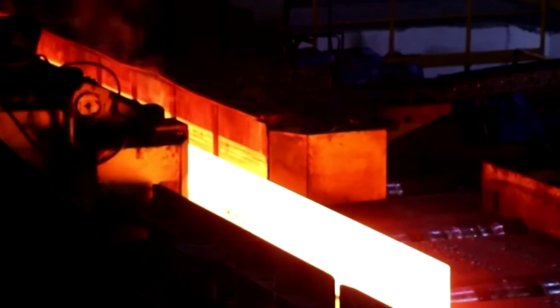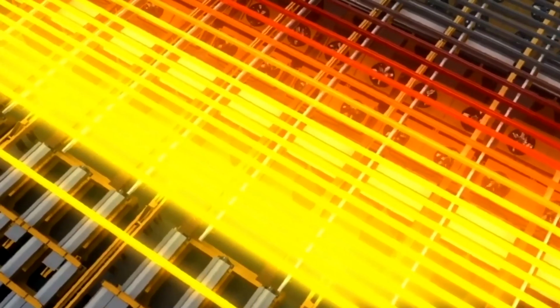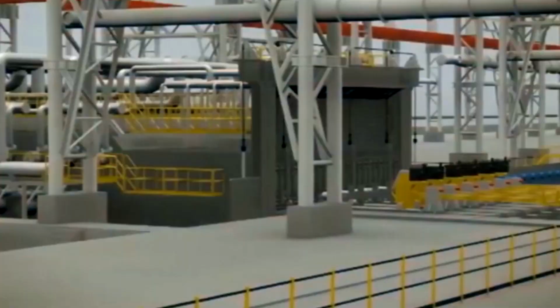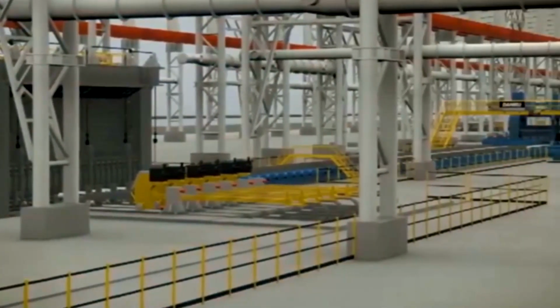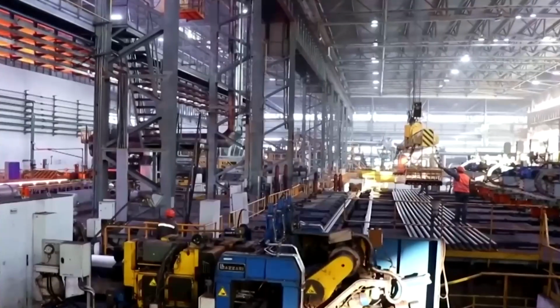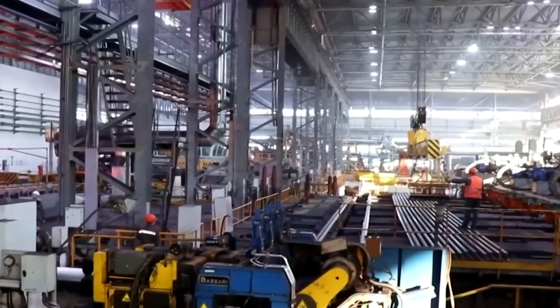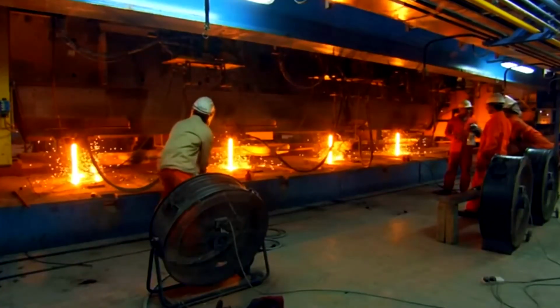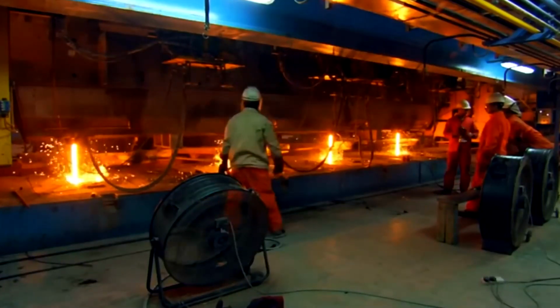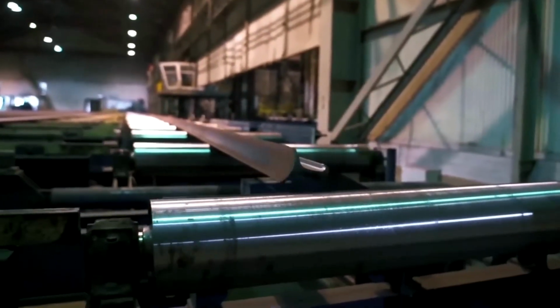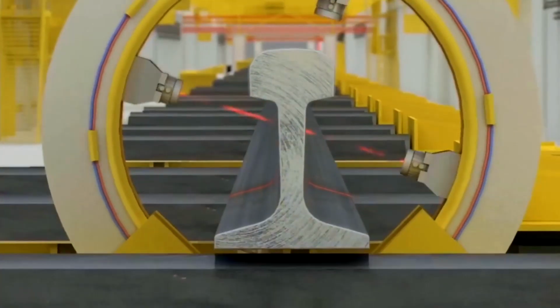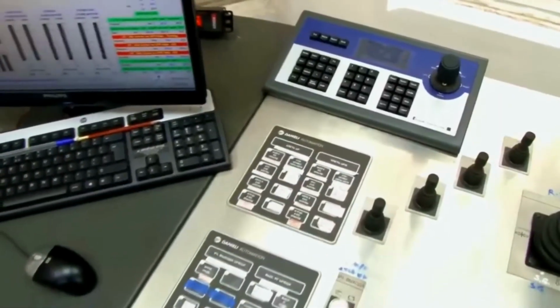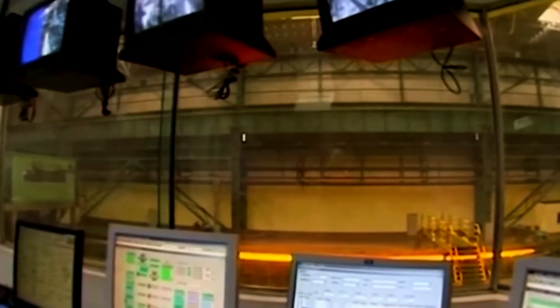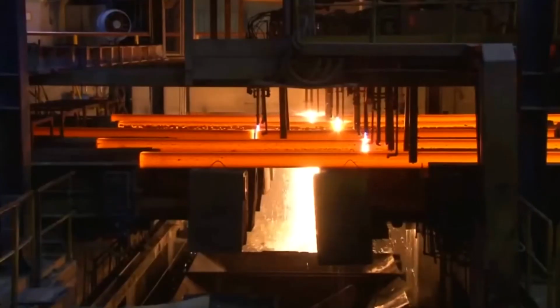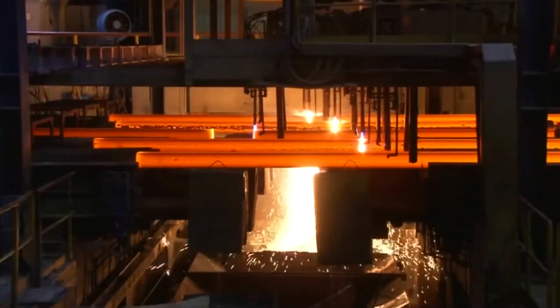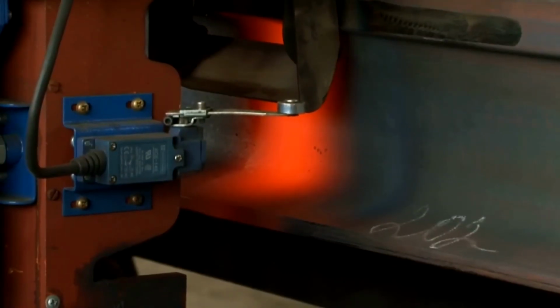Immediately after leaving the mills, the rails pass through a high-pressure water spray system, where a dense mist envelopes their entire surface. The speed and volume of this water are meticulously controlled to guarantee uniform cooling along the rail's full length, preventing any warping or cracking. Following this rapid quench, the rails enter the heat treatment area. Here, reheating furnaces are programmed to perform precise cycles of quenching, tempering, or annealing, depending on the desired mechanical properties for the final rail.